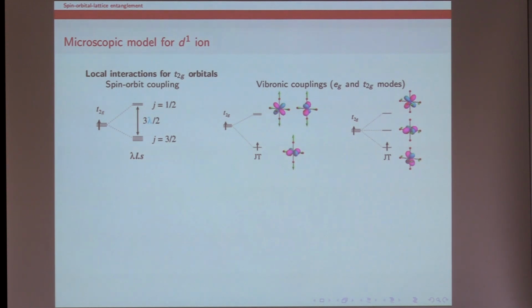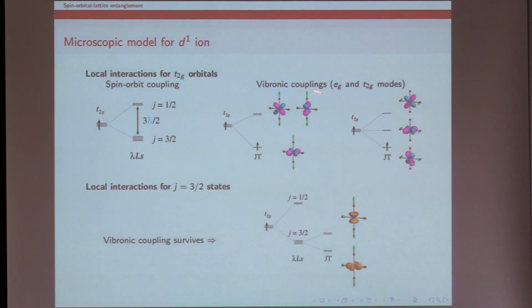Now I will explain our system. In our system, there is spin-orbit coupling, and T2g orbitals couple with two types of Jahn-Teller deformations. One is the doubly degenerate Eg one, and the other is the triply degenerate T2g deformation. And this vibronic coupling is not quenched by spin-orbit coupling, as explained yesterday. This can be intuitively understood by looking at the distribution of electrons in Γ8. There are two types of electron distribution, and for example, for this deformation, apparently these two electron distributions feel different potentials. So that's why there is Jahn-Teller deformation.